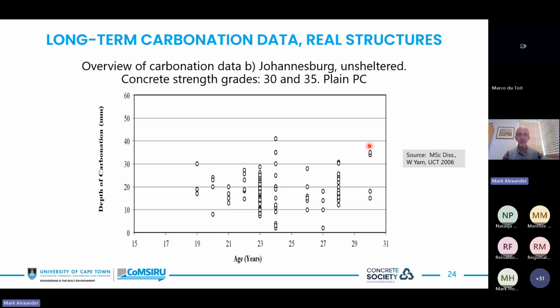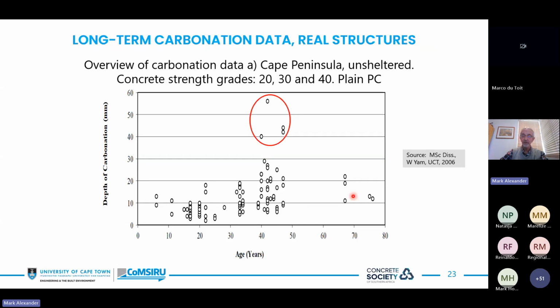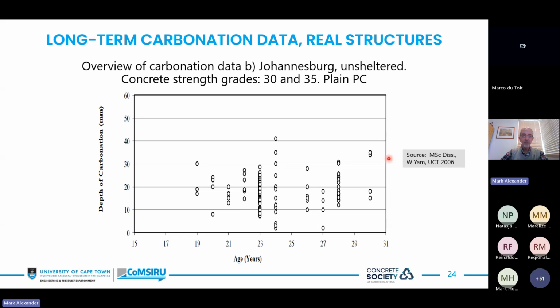If you look at the Johannesburg area, again unsheltered, and we've got 30 and 35 grade concretes here, a lesser time frame. But even here, carbonation is hardly exceeding 30 millimeters within the time here. Look, in the case of the Cape, we've got 80 years of data there. In the case of Johannesburg, 30, mainly from the Johannesburg motorways. And here again, maybe carbonation is not the huge issue we thought it might be.